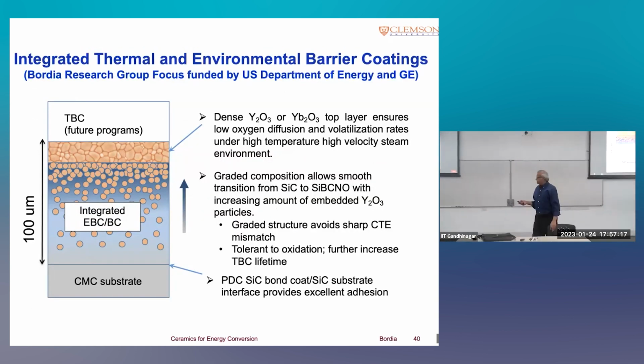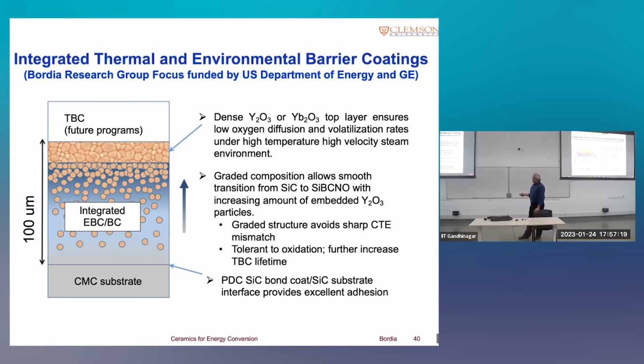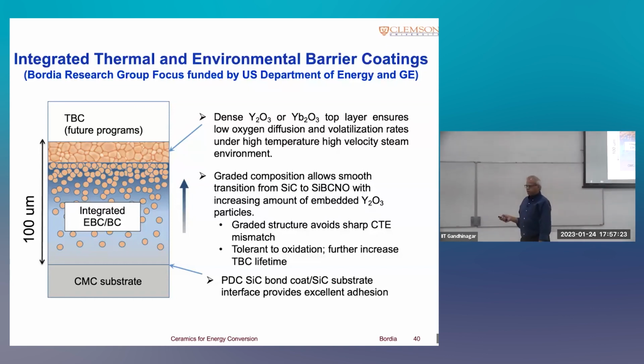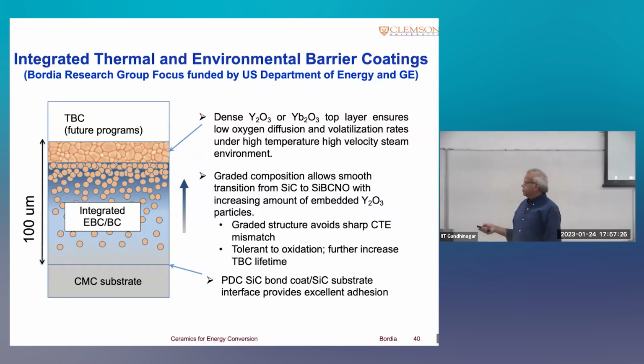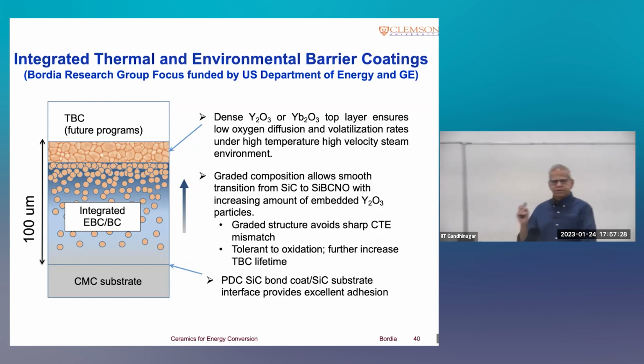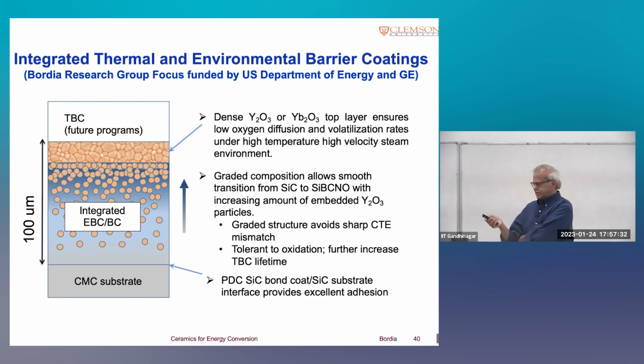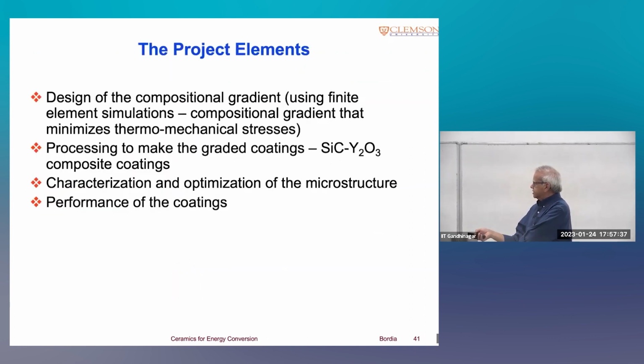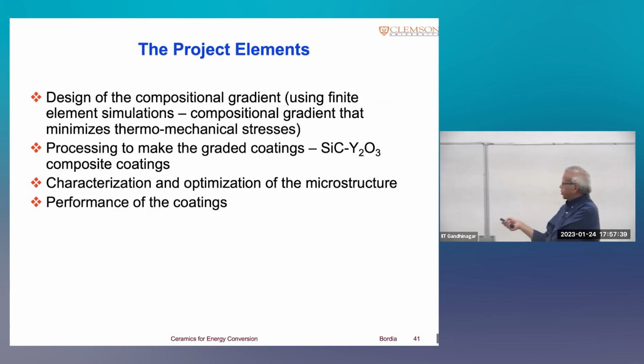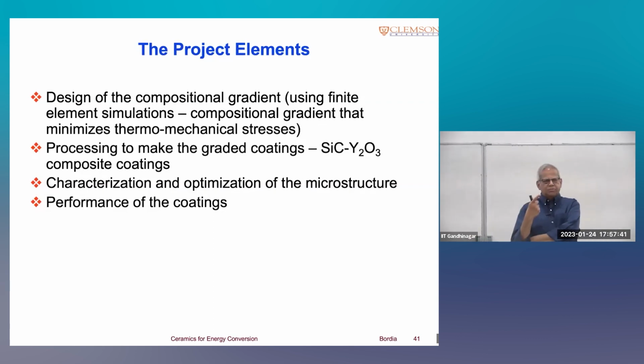And this is the concept that we've been working on. You have a silicon carbide composite, and we put this graded coating on it that ends up being an oxide coating, which is resistant to oxidation. And again, I'm going to show you just one set of results on it. So this is the whole program in which we develop the compositions of those coatings, the gradients in them, develop processing approaches to make them, and then we characterize the performance of these.